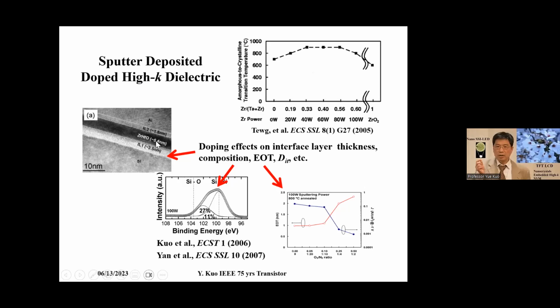For example, here we use zirconium-doped hafnium oxide. They form an interface layer. This interface layer is hafnium silicate. It's not a silicon oxide. So the interface itself is high K, and that's demonstrated by the XPS spectra. And this kind of device, we can make into EOT less than 1 nanometer. So sputtering can be used to deposit gate dielectric with EOT less than 1 nanometer.